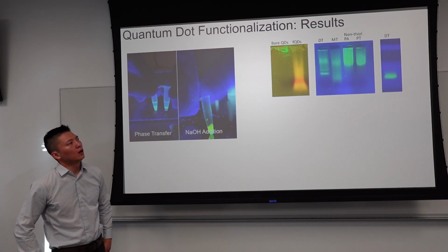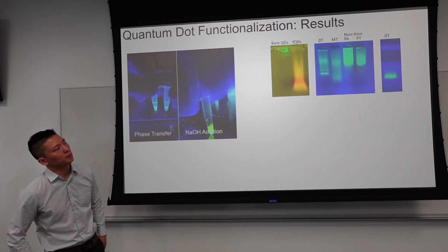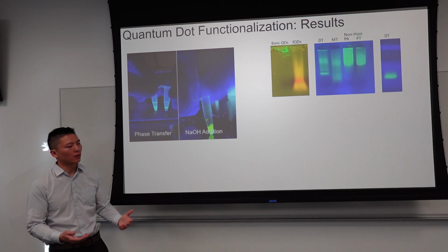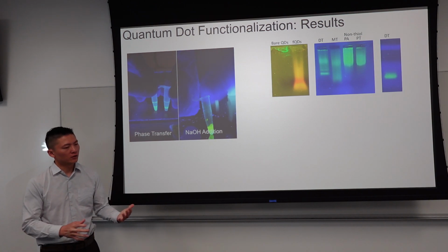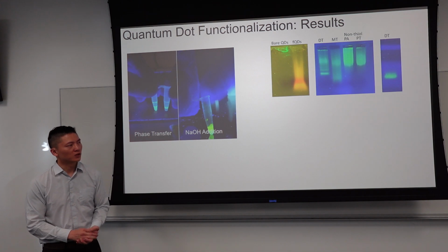Yeah, so over some time I've been able to optimize the dithiol so that I can get a single band. This helps us to indicate that, hey, all the nanoparticles tend to have similar mobility. Likely they have a similarly dense ligand shell.